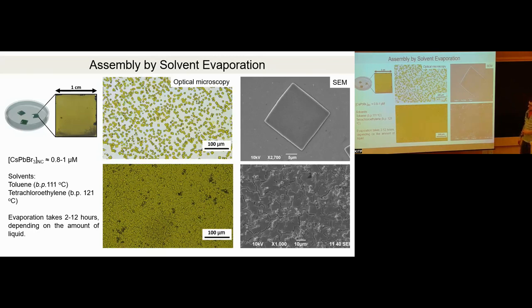So the way the experiment works is that you take a petri dish about 5 centimeters in diameter, 1 centimeter tall. Inside we put 3 silicon substrates, 1 square centimeter in area, and drop cast 30 microliters of solution onto each. Close the petri dish, leave the solvent to dry, and then depending on the concentration of particles, one can form isolated supercrystals or superlattice films, as we call them. For X-ray diffraction, there is really no difference between these two kinds of samples, but this shows some degree of control.